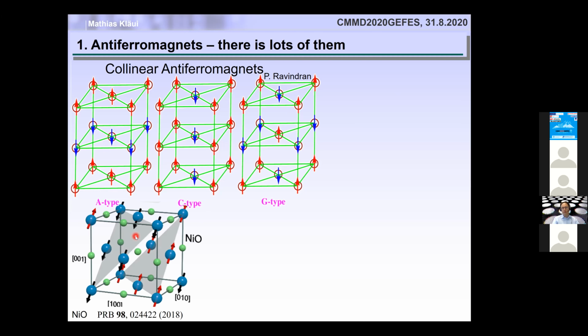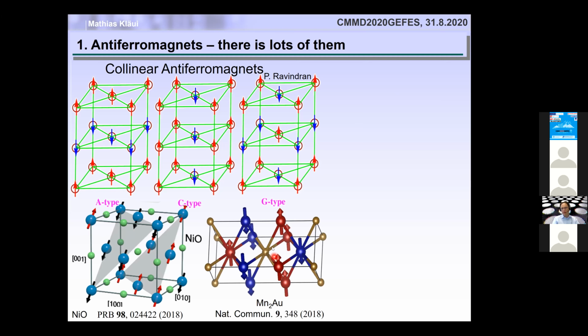For instance, in nickel oxide, we have a typical layered antiferromagnet, whereas in one of these 111 planes, the spins are all pointing in this direction, and in the neighboring 111 plane, the spins are pointing in the opposite direction. And now what is important, that in nickel oxide, we cannot distinguish between these two layers. However, there are also systems such as manganese gold, which I will go into in a bit more detail later, where you can actually distinguish between the blue and the red spins, because the two atomic positions are not identical, not equivalent.